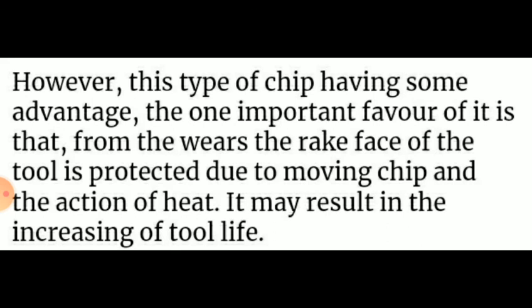This type of chip has some advantage. One important factor is that the rake face of the tool is protected from wear due to the moving chip and the action of heat. So it may result in an increase of tool life. The following conditions are favorable for formation of built-up edge: low cutting speed, small rake angle, coarse feed, large uncut thickness, and insufficient cutting fluid. That will result in the built-up edge.